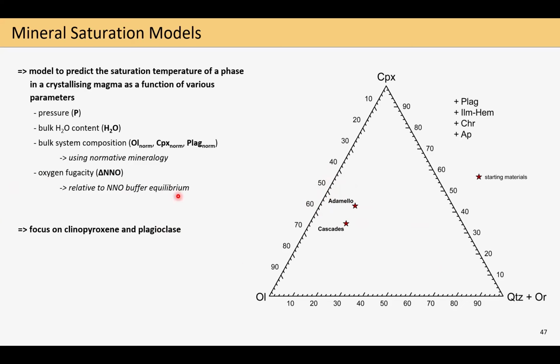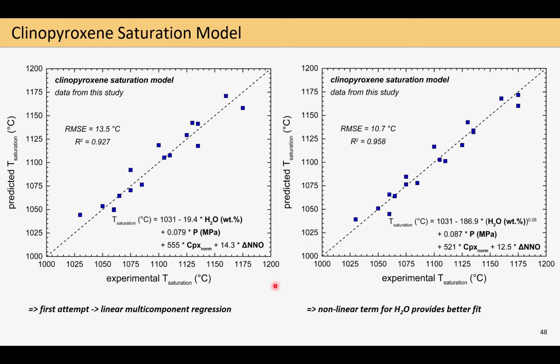And so far for these mineral saturation models, I was focusing my efforts on clinopyroxene and plagioclase, and let's now shortly have a look at my first attempts. So first, for clinopyroxene here, I did a simple linear multi-component regression on my experimental data, which then gave me this saturation model equation. And in this plot, I show you the predicted saturation temperature using this equation plotted against the experimental saturation temperature based on my observations from the experiments. And here you see already that this first quite simple model already seems to work quite well. So we have a relatively low error of estimate and a high R-square.